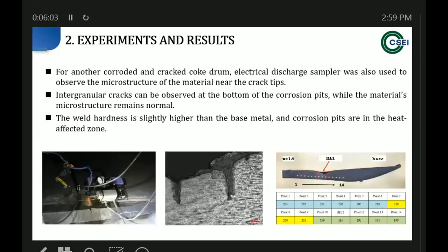And next, in case two, we also studied another one. This is a cracked coke drum, and we can see the crack initiation at the bottom of the corrosion pits. This material microstructure also remains normal, and we also tested the hardness.